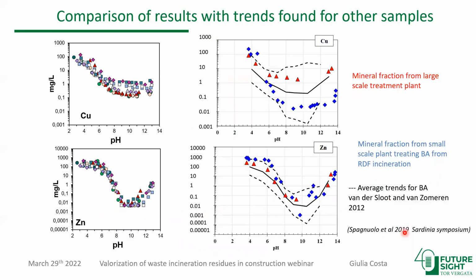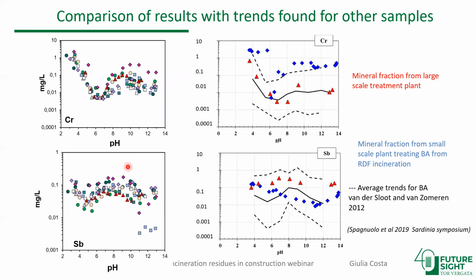Now, if you want to compare these results of the pH dependence test to those reported in the literature for bottom ash of worldwide origin, so before treatment, as we reported in a previous study, and also results of our previous investigations on other types of mineral fractions, we see that these samples are very much in line with average bottom ash behavior, both for copper and zinc. For chromium, we're a bit at the upper bound of the average values, especially looking at sample 4. Then for antimony, it is again always in the high range of the values reported in the literature for bottom ash, except for these lower values at alkaline pH.